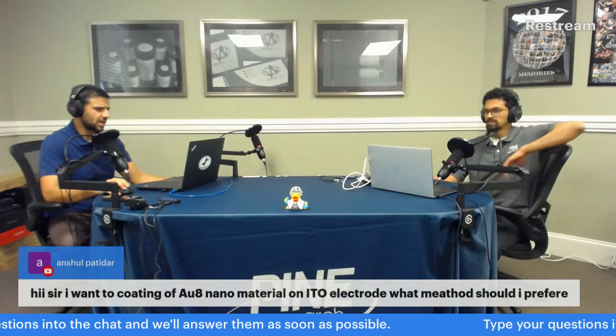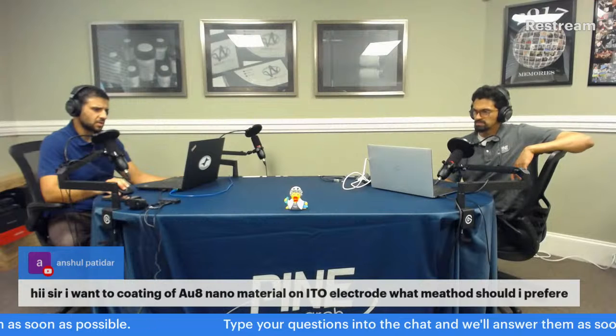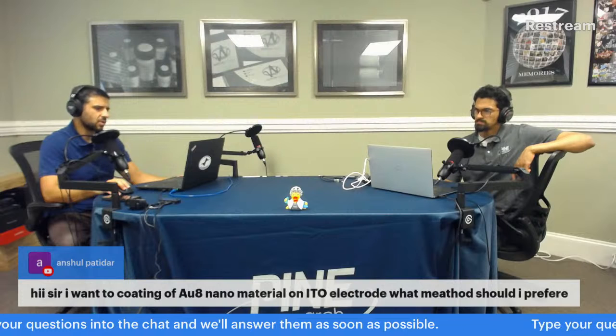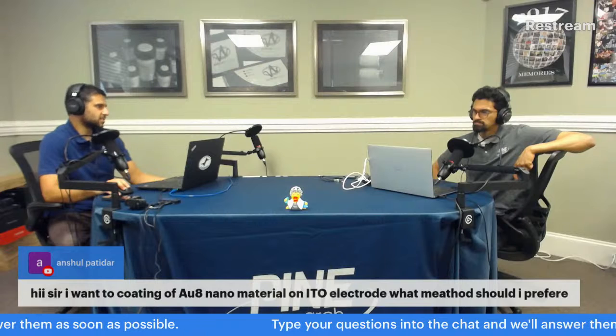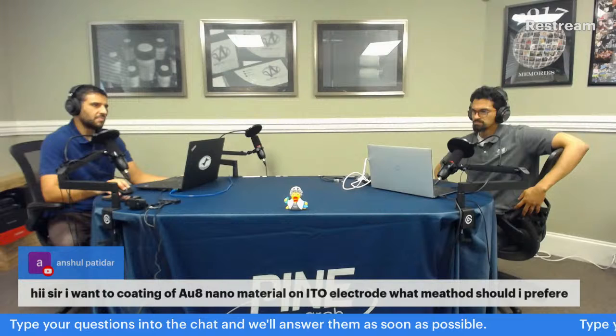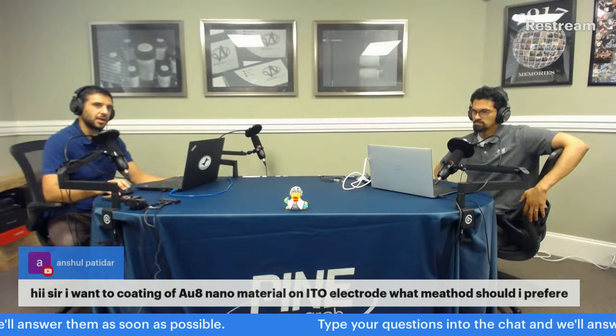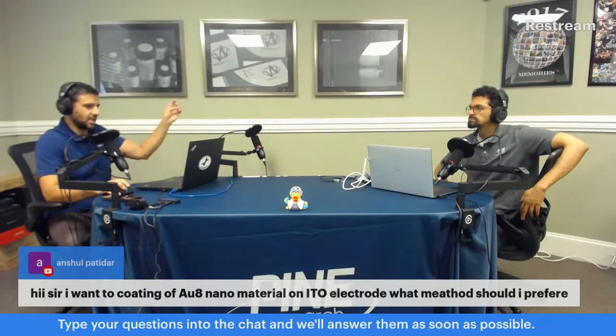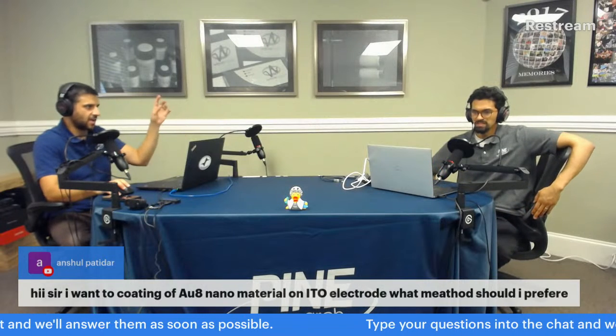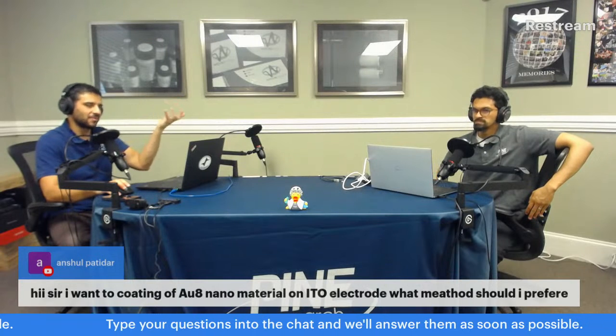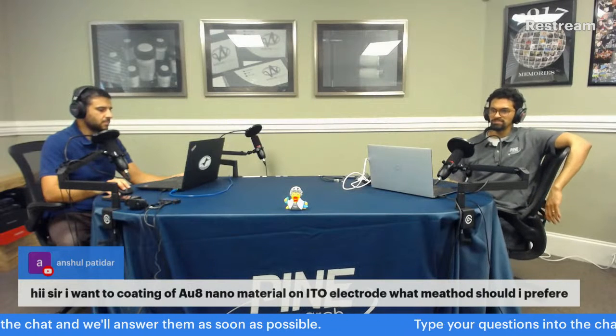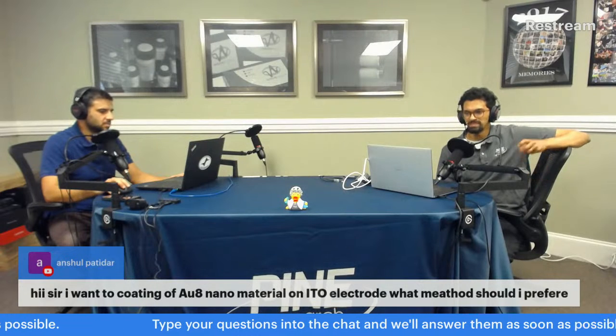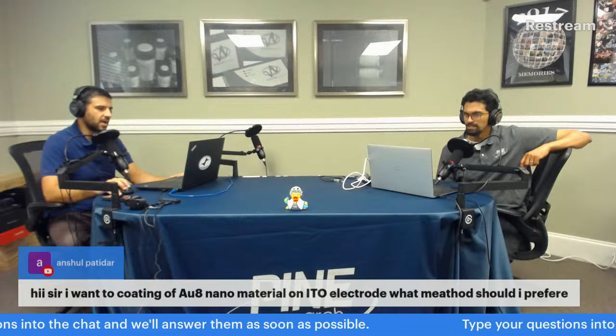Apologies for that. It looks like Anshul had some questions about gold and ITO, and Chris was answering them. You're talking about putting gold onto ITO, and Chris was saying that physical vapor deposition might be an option. I think typically putting a coating on ITO usually requires chemical vapor deposition or atomic layer deposition, ALD. Those typically involve an oven or a tube furnace with a carrier gas. It's heated up, you have a sample holder where you put your ITO, and you send material through a tube or sputter at it, and it slowly builds up a layer. I think I'm basically describing ALD. In this case, it makes eight-gold-atom nanoclusters, which is what I think this person is trying to do.